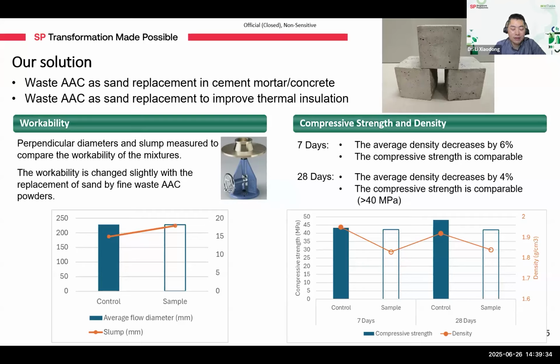We started by conducting a series of workability tests, including the perpendicular diameter measurement and the slump testing. These tests help assess how easy the modified mix is to work with on site, whether it can be mixed, poured, and finished without major adjustments. The results show that the substitution had only a minimal impact on the workability, making it a practical solution for real-world applications. We then evaluated the mechanical and physical performance of the modified cement mortar.